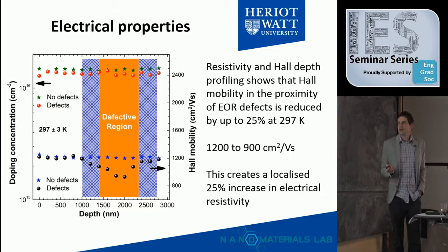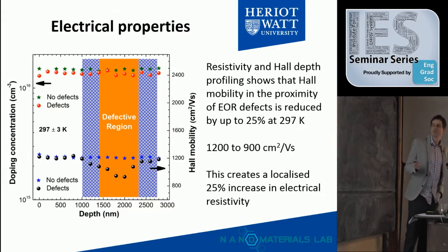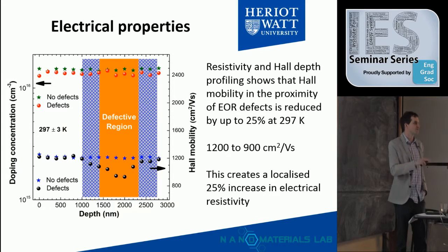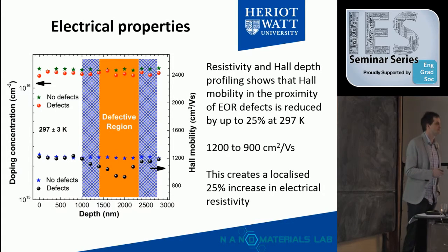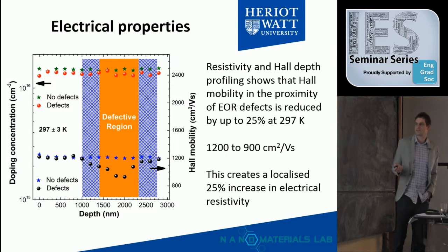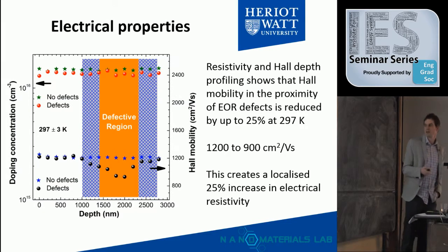And at this stage as well, we weren't particularly thrilled with what we saw, because we basically saw that in the ones without defects, the properties were fine. But where we had a lot of these dislocations, we particularly saw the mobility of the carriers in the material reduced. This is obviously not a good thing.